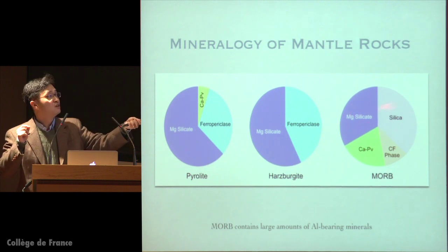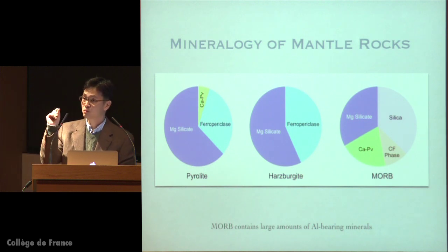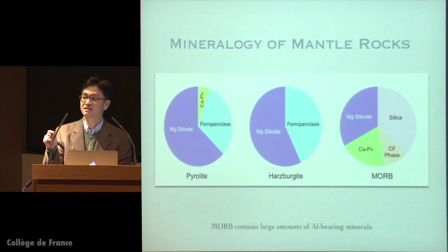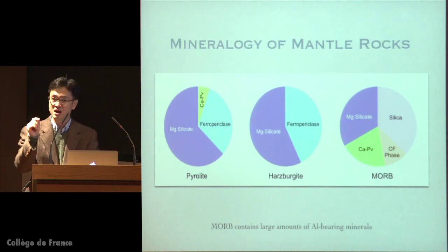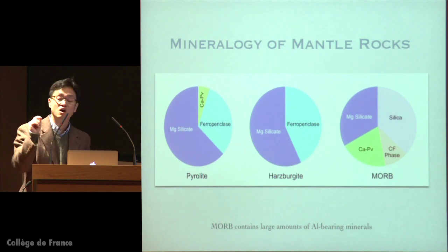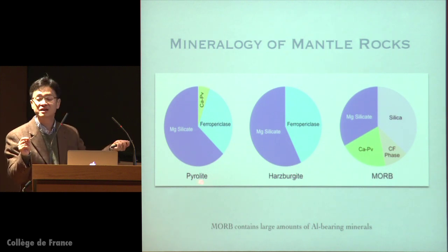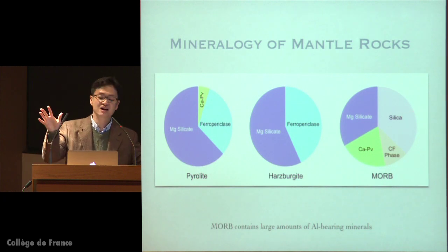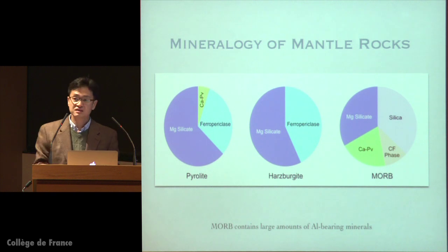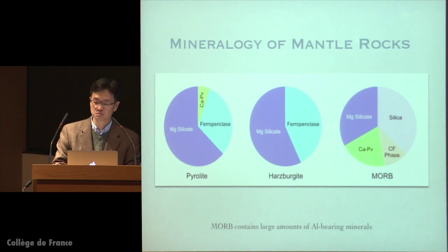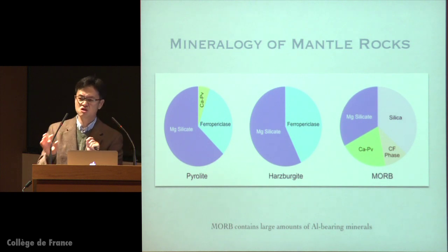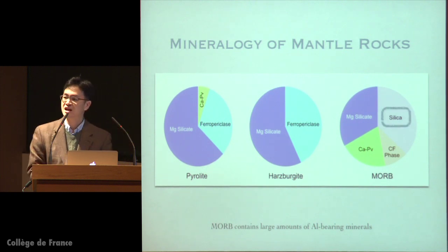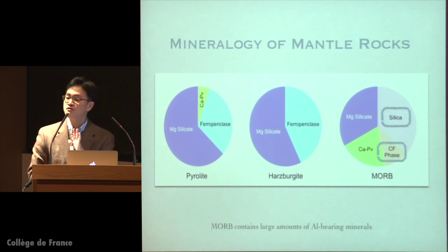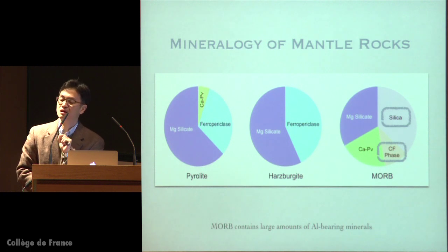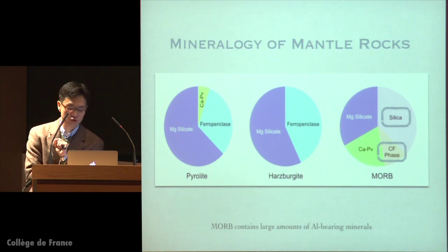As you can see, the concentration of magnesium silicate perovskite or post-perovskite is significantly lower. It's about 30%, whereas your pyrolitic mantle produces about 70 to 80%. And more importantly, you have other secondary phases that didn't exist in harzburgite or pyrolite, which are silica, SiO2, or stishovite, and the so-called calcium ferrite phase, and also calcium perovskite. But don't worry about understanding these individually. What is important is that silica contains some iron, aluminum, I'm sorry, and the calcium ferrite type phase contains both aluminum and iron. So these are two good candidates to influence the thickness of the post-perovskite transition.